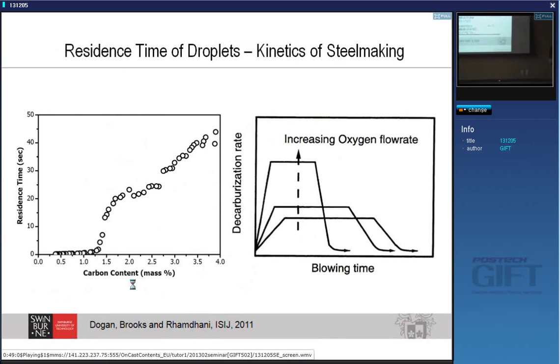So this is the reinterpretation of oxygen steelmaking that I have developed with my co-workers. And what we say is that early on, you have a lot of carbon. And the residence time of the droplets may be 30, 40, 50 seconds. Then as the blow continues, the droplets become dense. They don't spend so much time in the emulsion. So therefore, the whole reaction slows down. This reinterpretation of steelmaking is called the bloated droplet theory.